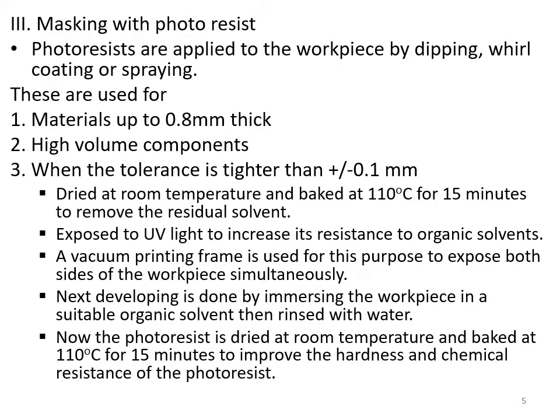Masking with photoresists. Photoresists are applied to the workpiece initially by dipping, whirl coating or spraying. They are used for materials up to 0.8 mm thickness. These photoresists are especially used for high volume components, when the tolerance is tighter than plus or minus 0.1 mm. They are dried at room temperature and baked at 110 degrees Celsius for 15 minutes to remove the residual solvent.